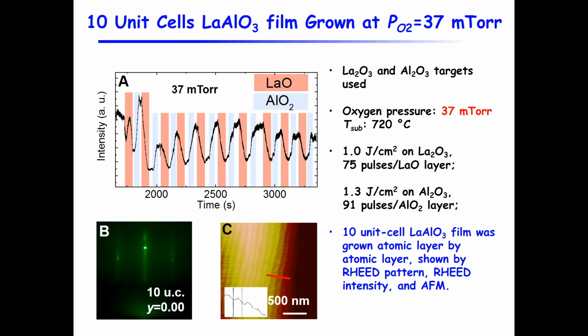People ask, why don't you go even higher? When we go even higher, we cannot maintain layer-by-layer growth. In this case, if you look at the RHEED intensity oscillation for 10 unit cells, we maintain very nice oscillation of the RHEED intensity. The pattern shows very nice films, and AFM also shows smooth films.